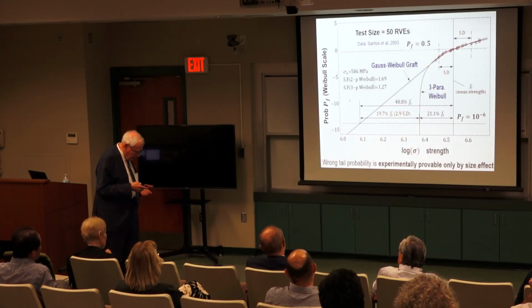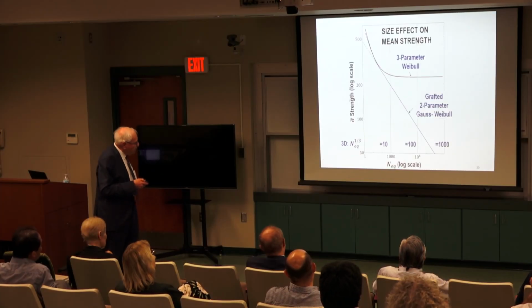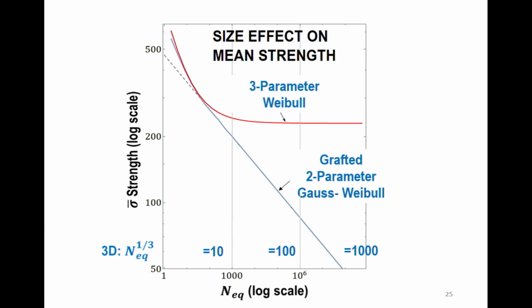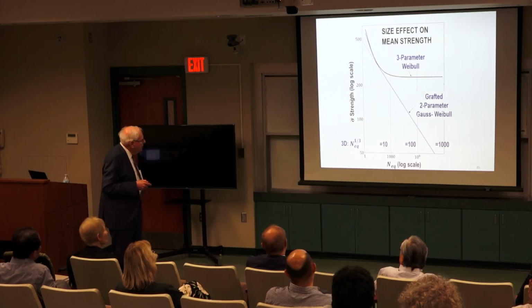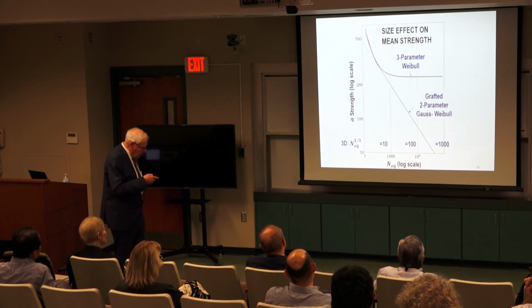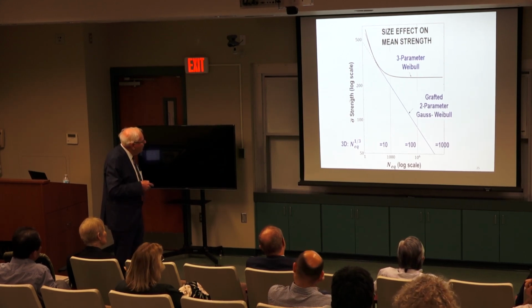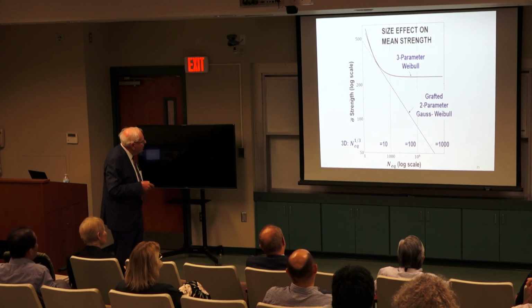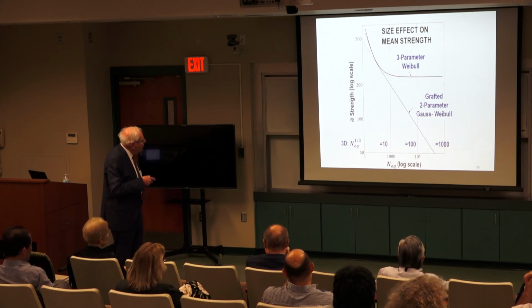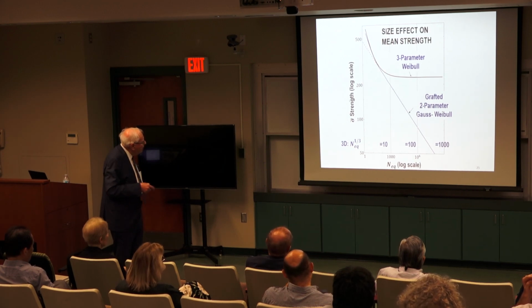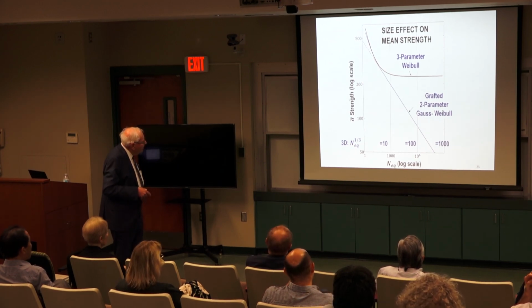Now, imagine a size effect. So, in terms of size effect, this is the size of testing. And in ceramics, they say we tested actual size, we are not interested in size effect. But the difference is enormous. If you extend the 3-parameter Weibull distribution of Santos, you get this curve. If you extend it according to our model, it agrees here, but it's a straight line, and you see the enormous difference here. You might say this specimen is too big.